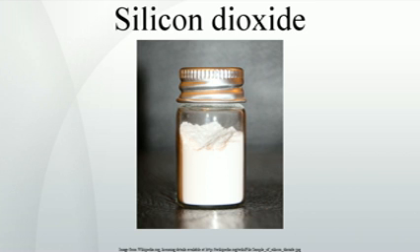Stishovite, the higher pressure form, in contrast has a rutile-like structure where silicon is 6-coordinate. The density of stishovite is 4.287 grams per centimeter cubed, which compares to α quartz, the densest of the low-pressure forms, which has a density of 2.648 grams per centimeter cubed. The difference in density can be ascribed to the increase in coordination, as the 6 shortest SiO bond lengths in stishovite, 4 SiO bond lengths of 176 pm and 2 others of 181 pm, are greater than the SiO bond length, 161 pm, in α quartz.